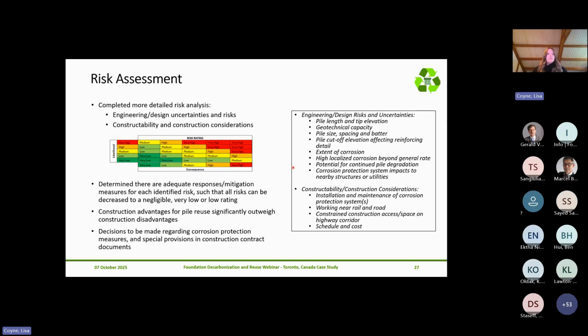It ranged from physical things like the pile length and tip elevation, which then, of course, feed into pile capacity. Was the pile size shown on the design drawings and discussed in some notes? Is that the right pile size? It's unlikely to be a lighter pile section, but nonetheless, a check on that. Spacing, batter, pile cutoff elevation, probably less critical in terms of capacity assessment, but it has an impact around reinforcing steel details for replacement of the pile caps. And then moving on into the extent of corrosion and the corrosion rate and high localized corrosion beyond that general rate, potential for continuing degradation, impacts on nearby utilities.